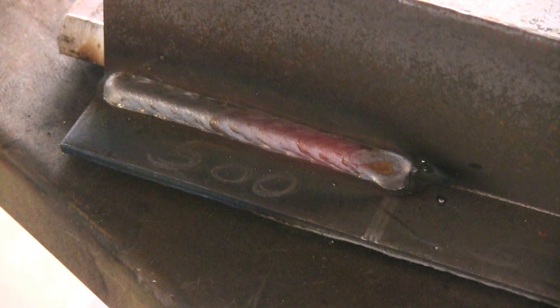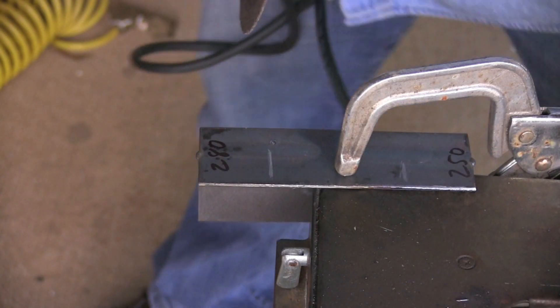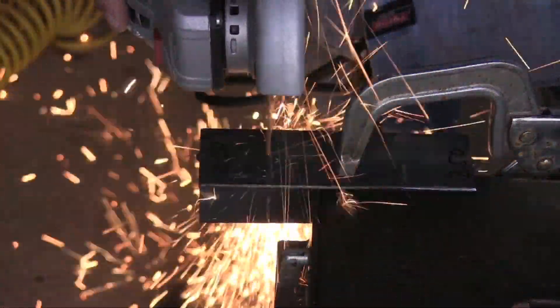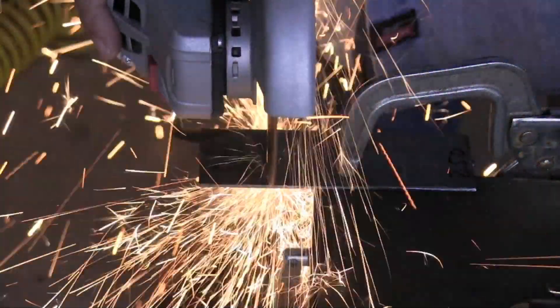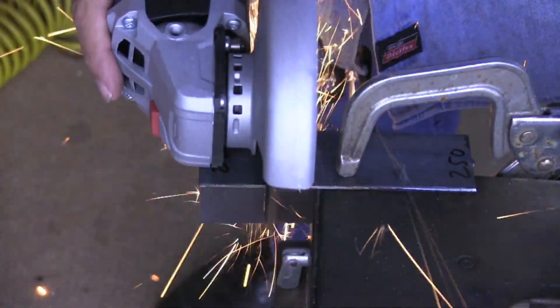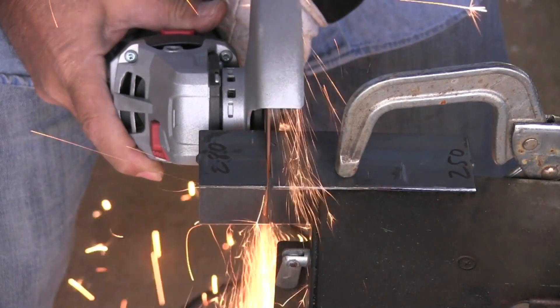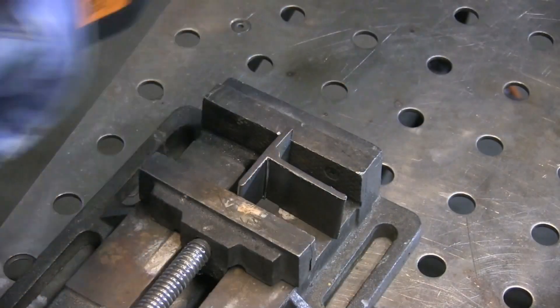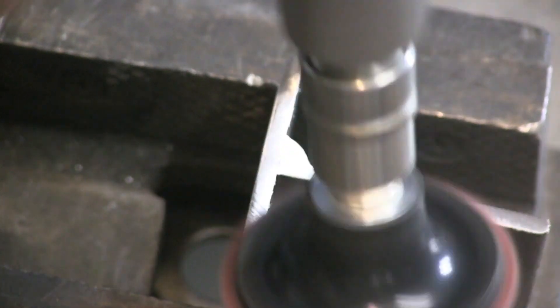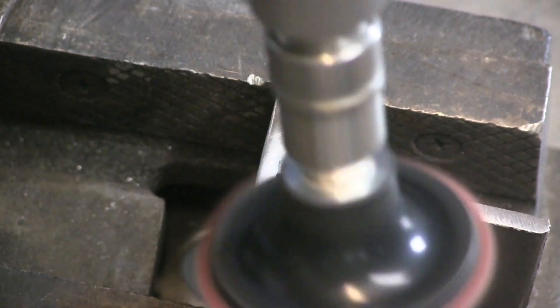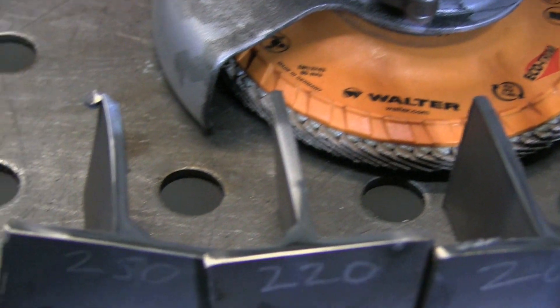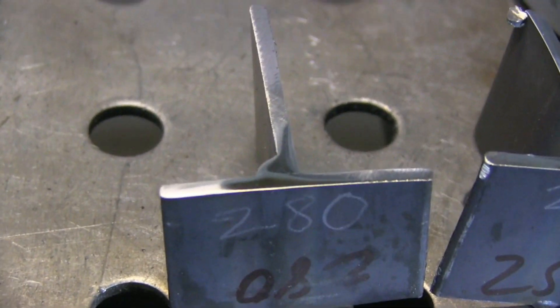Now it's time to do some tests. You don't need anything fancy to cut cross sections with. I'm just using an angle grinder here, 6 inch Metabo with a slicer plus cutting wheel. And actually, one cutting wheel lasted about seven cuts without even any noticeable wear. Pretty impressive. Probably took roughly 30 to 45 seconds per cut. A little quick hit with a flap disc here and followed up by two different grits of scotch-brite pads, red followed by blue. And that's about all you need to be smooth enough to give a result from an etch.